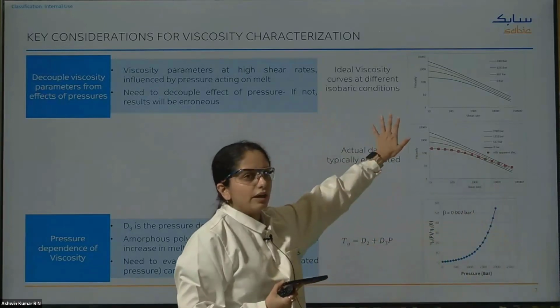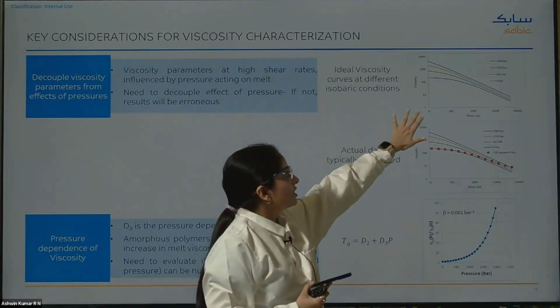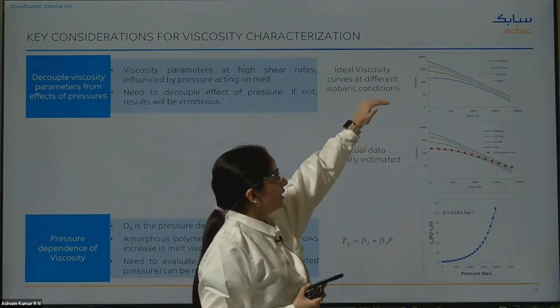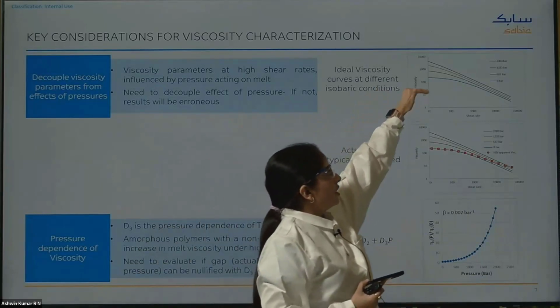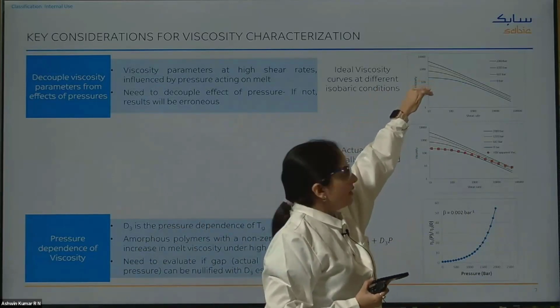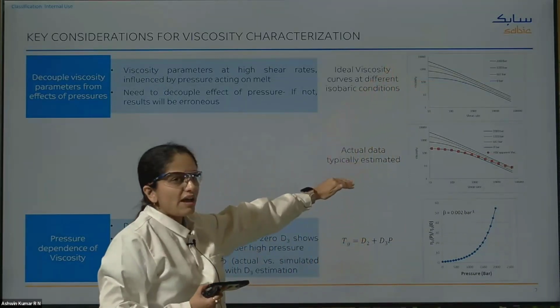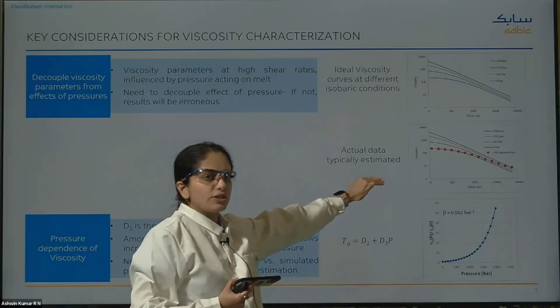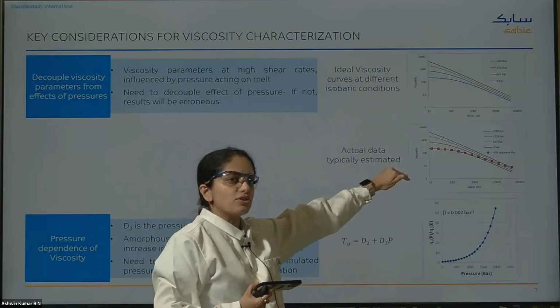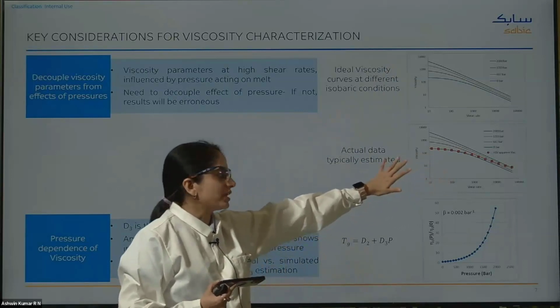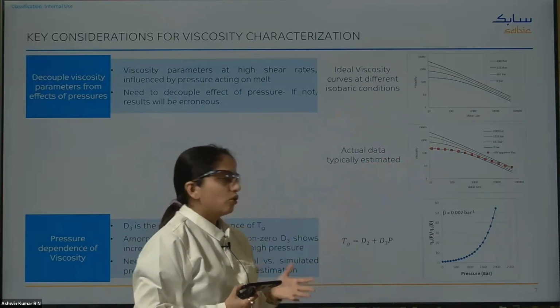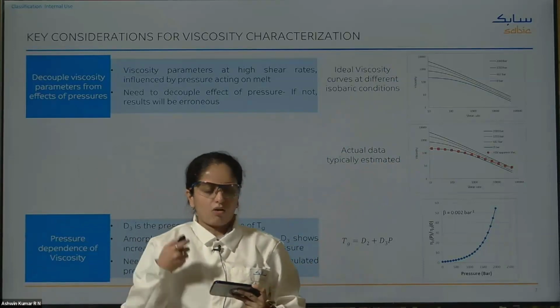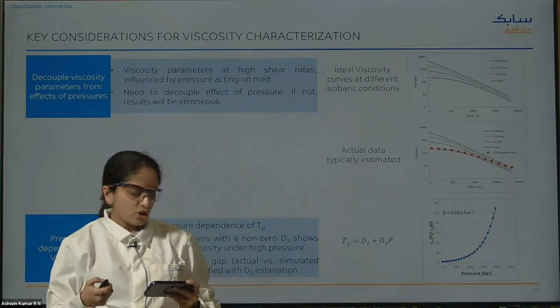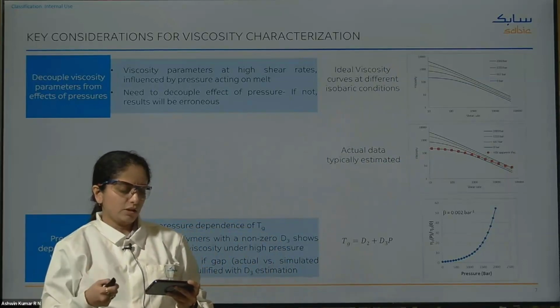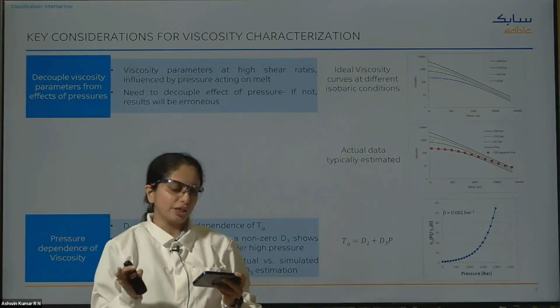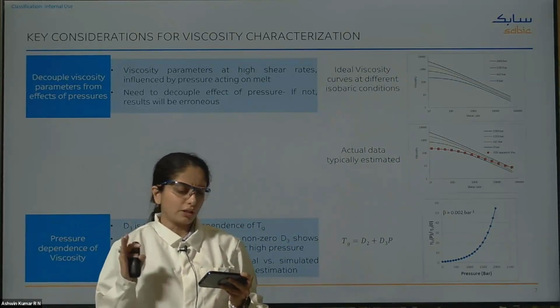Here we see a graph of viscosity as a function of shear rate, a representative graph measured at different isobaric conditions, wherein we have 0 bar, which is the ambient pressure, and then the higher pressures. We also have an estimated data set wherein we have apparent viscosity, which is converted from the measured viscosity. It is fitted onto the measured viscosities, and we see that it gives a good correlation. So what exactly do we do to determine this D3 parameter? Currently we have a method to address this effect of decoupling the shear rate from the pressure during characterization.